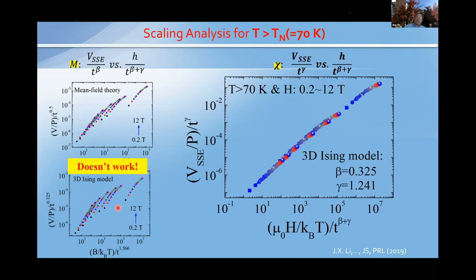So we tried a different one, right? We treat the spin Seebeck voltage as a quantity proportional to magnetic susceptibility. In order to do that, we need to switch to different exponents, which are shown here. So we use the three-dimensional Ising model exponents. Actually, it really worked. Mean field doesn't work either.